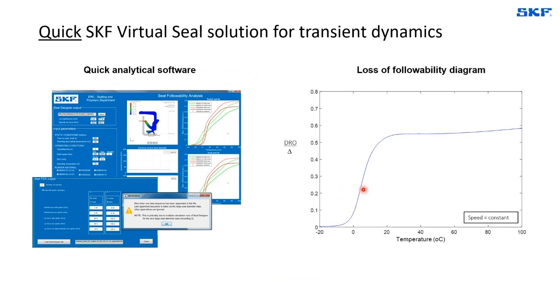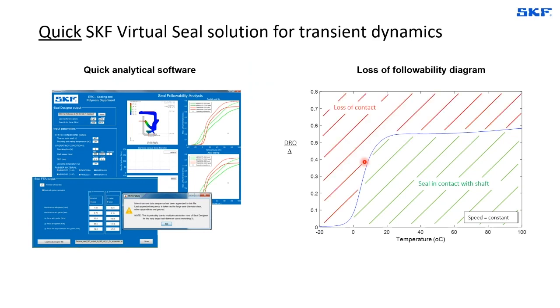So I want to take a moment to explain what we see here. On this so-called diagram for loss of followability, followability being the capability of the seal to remain in contact with the shaft across a range of application conditions, we have the dynamic runout versus the interference level on the y-axis, versus the temperature on the x-axis. For a constant speed, this line is a boundary line where below the line the seal remains in contact, based on our analytical model, and above the line the contact is lost. So we are able to understand what configurations would be dramatic for our seals. Please remember this diagram, as I will come back to it at a later stage in the presentation.